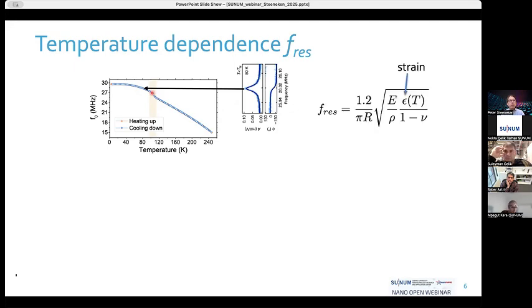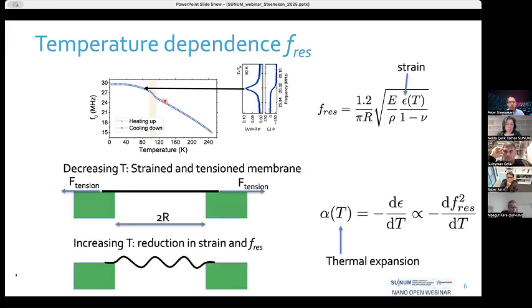To understand it, we should realize that this membrane is like a string, like a guitar string, which becomes tensioned when there is stress on it. And the stress is caused by the temperature change. The substrate, the size of the membrane by which it's clamped, is expanding less or contracting less than the membrane itself. So that causes the contraction of the membrane, I think I have a picture here. When you cool it down, the membrane contracts and it becomes tensioned and the resonance frequency is increasing. So strain is generated, so you get this tension.